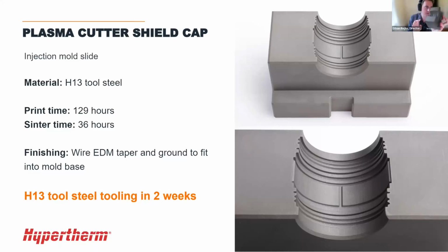It's just going to run in the background, set it up. It's going to run over the weekend, over your holiday. Hopefully you're sitting on the beach while our printer just keeps whirling away and producing parts. After the parts came out of the furnace, they did a little bit of wire EDM to a taper on one side for the slide, and they ground and fitted into the mold base. So ultimately, they were able to deliver an H13 tool in just 2 weeks. So for them, dramatically accelerated the time to produce this tool.